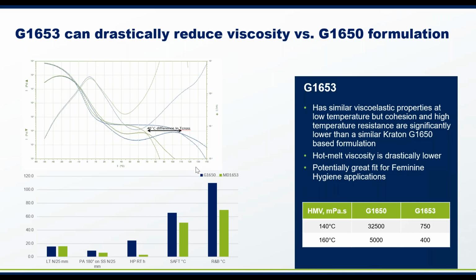In this graph, again, we have similar data that David showed previously, where we're just comparing G1650, which is a more conventional Kraton G grade, with, in this case, G1653. And so again, loop tack properties, peel adhesion properties, even the SAFT properties are relatively similar with G1653, but we also get much lower hot melt viscosity, right? And that's kind of where we're looking here. If there's a system that enables lower viscosity, then this could be reformulated or possibly tailored to even boost these properties further if that application had that desired set.